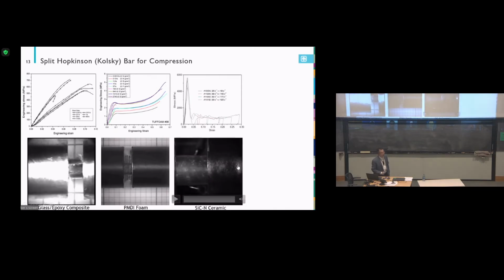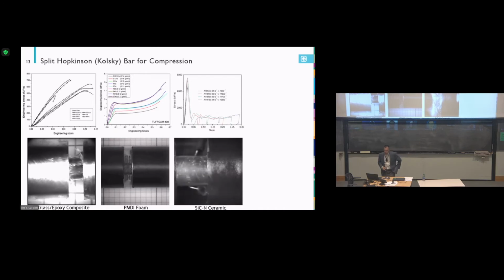And this is ceramic, very high strength ceramic. You can see up to nearly 6 gigapascal strength. You can see how the ceramic fractures, just suddenly cracks, then totally shatters. Very, very brittle. You can see the failure strain is only up to 2%.